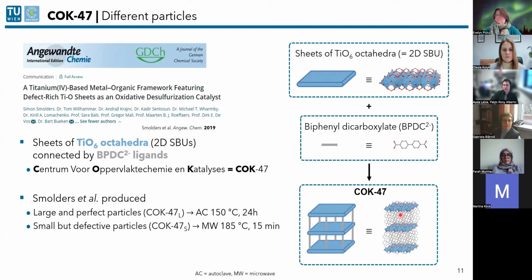So actually, there is two ways of preparing them. You can make them defective, in this case, defects meaning missing linker defects, to introduce some porosity. So these were the two synthesis procedures that were described, the one through autoclavation, very classic MOF synthesis, and then you get COK-47L, so L for large particle. And if you use microwave irradiation, high temperatures and very short times, then you get COK-47S, S for small particle.